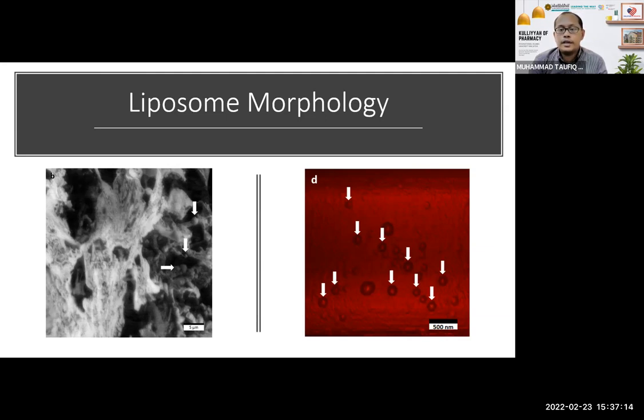But when you freeze dry it, because you want to put it under SEM and you freeze dry it, some of them might not be cryoprotected enough. So some of them, when you rehydrate it back, you will find that the size changes. So these are the things that you have to do in order to check whether your formulation will fit the need of what you want to do with that formulation itself. So for example, in this case, I found that between 400 to 450 is good enough to make sure that the trehalose protects the liposomes, so that during the imaging, we can see the supposed liposomes in there. And also that when we rehydrate it back, we can get the same size of liposome from the solution.